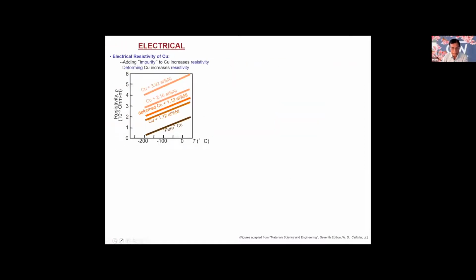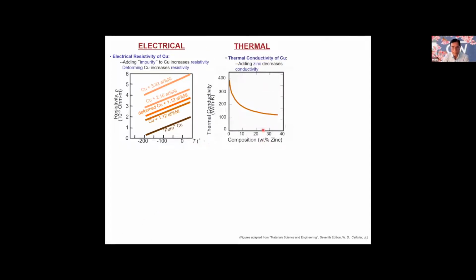So here are some of the properties changed by adding some impurity. This is pure copper. This is the resistivity we are talking about, and this is thermal conductivity. In the first graph, you can see that with the addition of nickel, the resistivity of the copper increases. With the addition of zinc, thermal conductivity goes down.